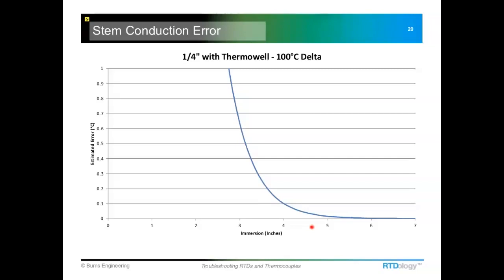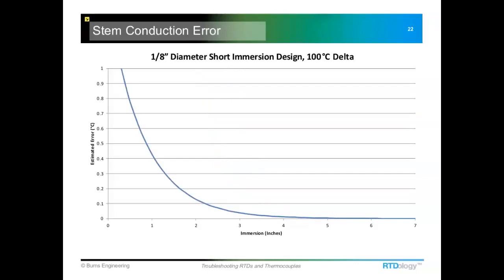This was also done with a 100 degrees C temperature difference between the process and the ambient conditions. So if your process and your ambient temperatures are the same, of course, you're not going to have any stem conduction error, but the farther they get apart, the magnitude of that error increases. Now, if we go with the direct immersion probe, we can see that line shifted off to the left here, a little shorter immersion. We still get a good accurate measurement. Now we're down to about 3.5 inches. And if we were to go with a smaller diameter probe, you can get by with even less immersion length to overcome that stem conduction. As we can see there with the 1/8 inch, now we're down to almost 2 inches of immersion to maintain a good accurate measurement.